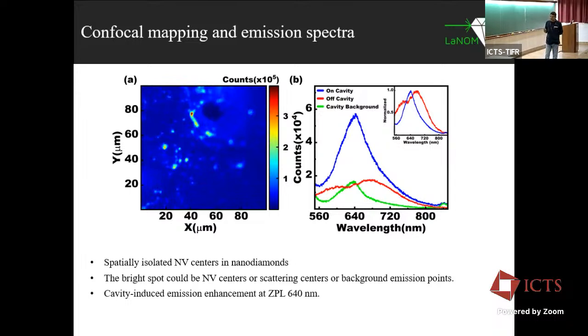What happens in our experience? If you look at the spectra, this green curve, for example, looks exactly at 640 nanometer. And if I zoom into this green line and show it to anybody, everybody trusts me that this is a cavity mode at 640 nanometer. But this is actually background emission from the cavity, and it is getting enhanced due to the cavity. So it is not actually an NV center emission spectrum, even though it shows at 640 nanometer.